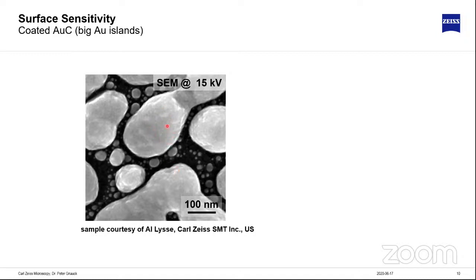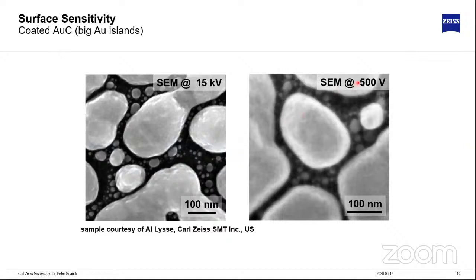If I want to visualize that in an SEM, what I need to do is I need to go to lower voltages. I need to become more surface sensitive. So I can do that. I can go down to 500 volts and I start to see some grainy structure on the surface. But we also notice that the resolution degrades due to chromatic aberrations.